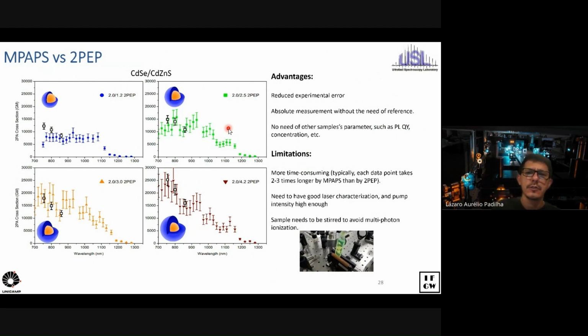However, there are limitations, which is that it's more time consuming. So you see, you have all this bunch of data for 2PEP. However, you have only 3 data points for MPAPS. And that's because each data point for this takes at least 3 or 5 times longer than each one of this. You need to have good laser characterization. So for 2PEP, if you have a good reference sample, you may not know what the pulse width of your laser is, but as you're using a reference, you don't really care about the pulse width.